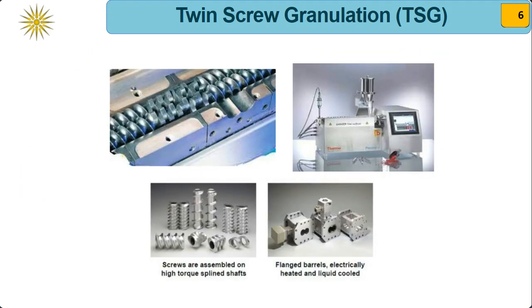An interesting part for twin screw granulation is that it uses exactly the same equipment which is typically used for hot melt extrusion or from the food industry or plastic industry. And this is the twin screw extruder. As you can see on the top right image, this is an 11 millimeter twin screw extruder, which comprises two main screws, and each screw comprises different screw elements which are assembled on high torque spline shafts. The shafts are placed in barrels where we can accurately control the temperature during the process, and basically this is the main principle where we can apply twin screw granulation.